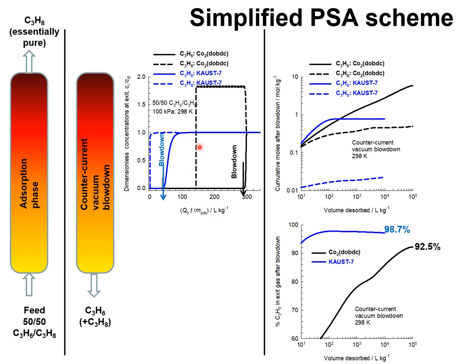I now compare the adsorption and desorption cycles for two different MOFs: Cobalt MOF-74 and KAUST-7, which have two different strategies for propylene-propane separations. The breakthroughs with Cobalt MOF-74 are indicated by black lines and those with KAUST-7 by blue lines. For Cobalt MOF-74, there is significant uptake of both propylene and propane, whereas with KAUST-7, propane is practically excluded from the pores. However, the uptakes of both components are significantly lower than with Cobalt MOF-74.